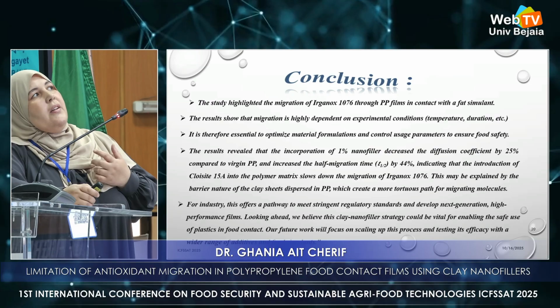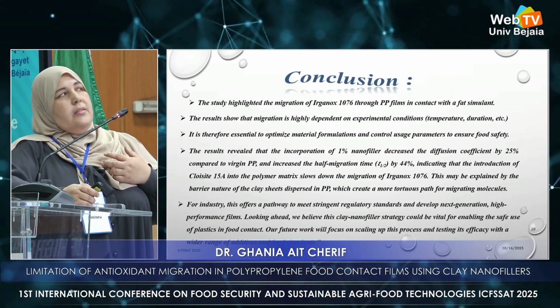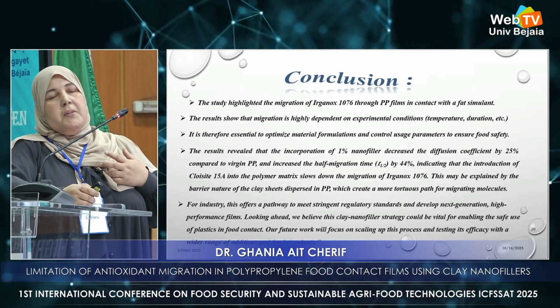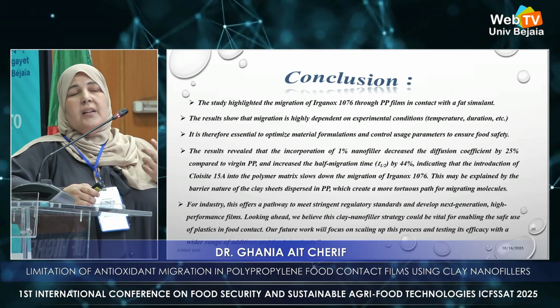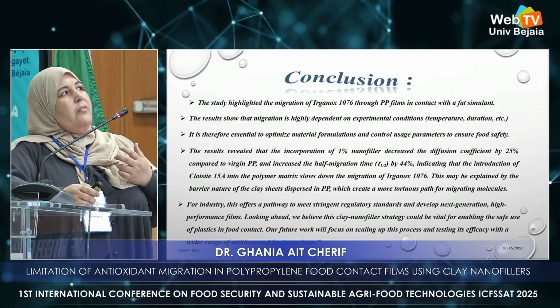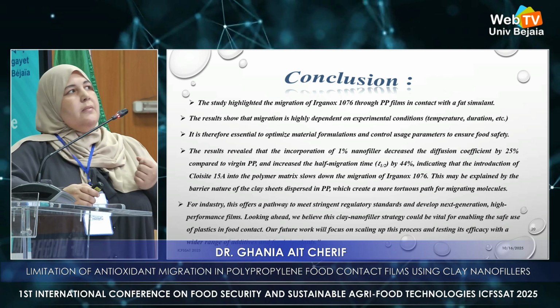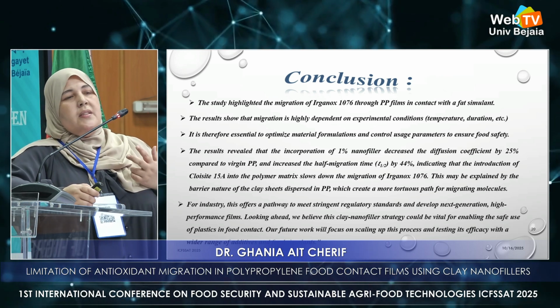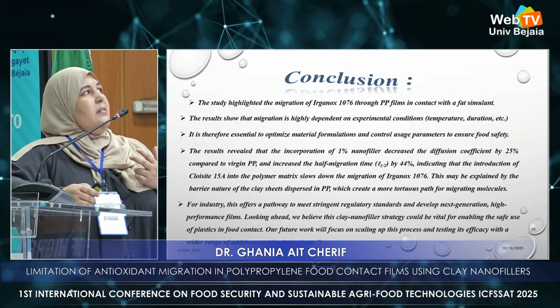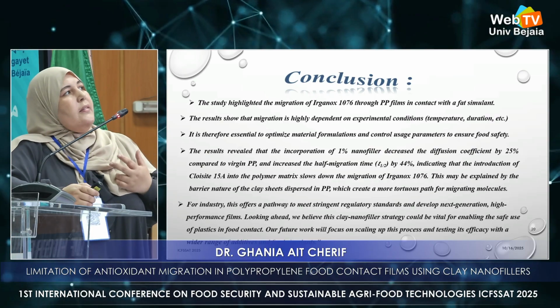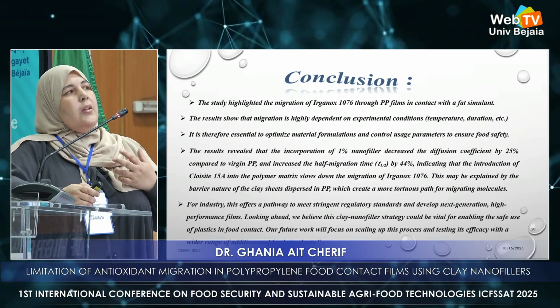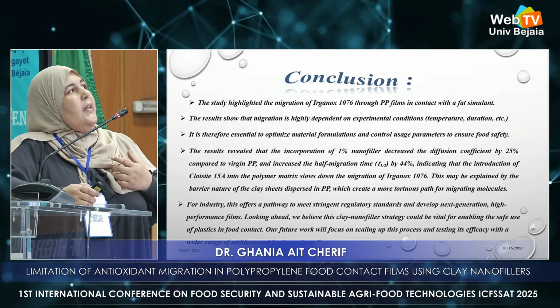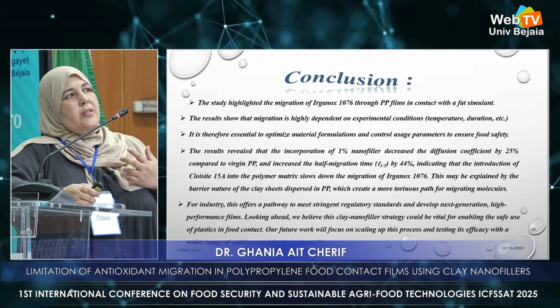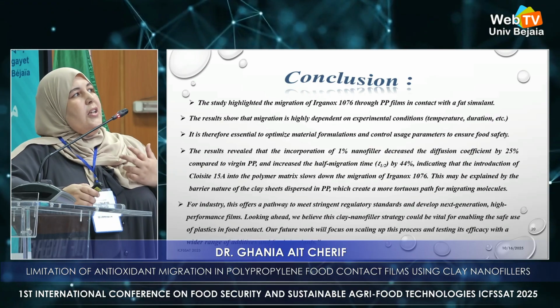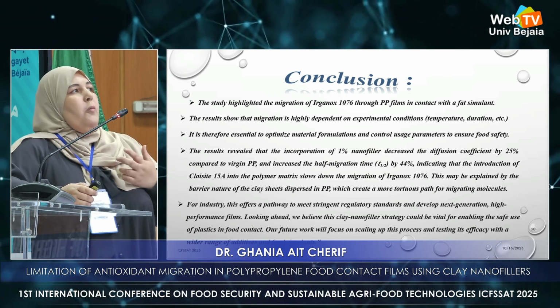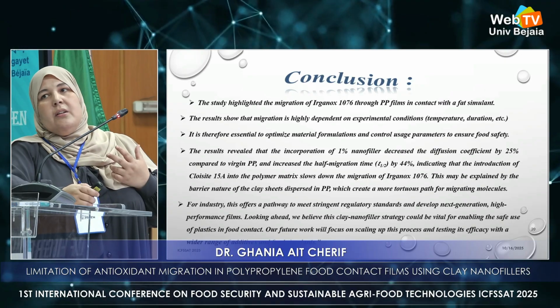To conclude, the study highlighted the migration of Irganox through PP film in contact with a fatty simulant. The results show that migration is highly dependent on experimental parameters like temperature and contact time. It is therefore essential to optimize material formulation and control usage parameters to ensure food safety. The results revealed that the incorporation of 1% of nanofiller decreased the diffusion coefficient by 25% compared to the virgin polypropylene and increased the half migration time by 44%, indicating that the introduction of Cloisite into the polymer matrix slows down the migration of the Irganox. This may be explained by the barrier nature of the clay sheets dispersed in the polypropylene matrix, which create a more tortuous path for migrating molecules.